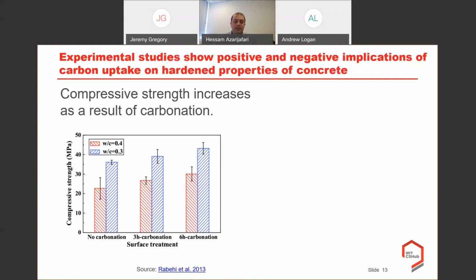Like here in this example, you can see that when the specimens are not exposed to any carbonation in the atmosphere, and when we have 3-hour accelerated carbonation with a huge quantity of carbonation, and 6-hour, we can see that there is an increase in the compressive strength in 2 different water to cement ratios. And this increase happens because of the water, which is released from the reaction of the calcium hydroxide, which helps the hydration continue.